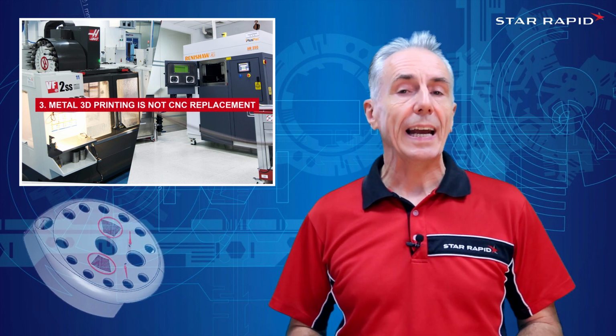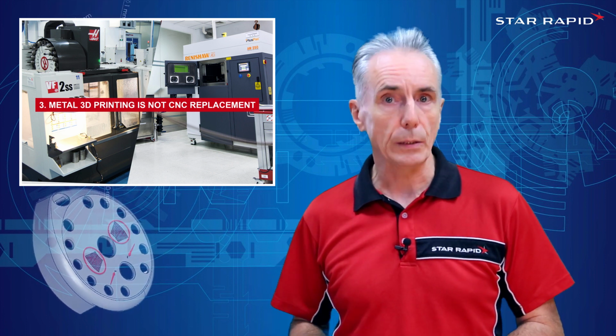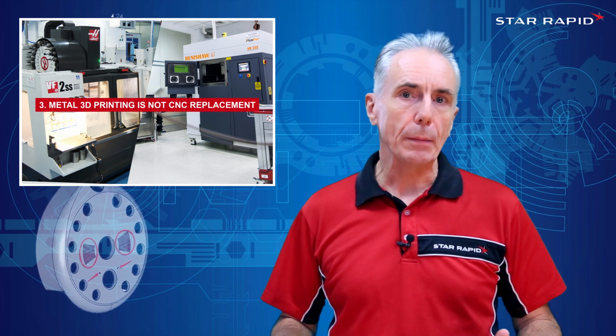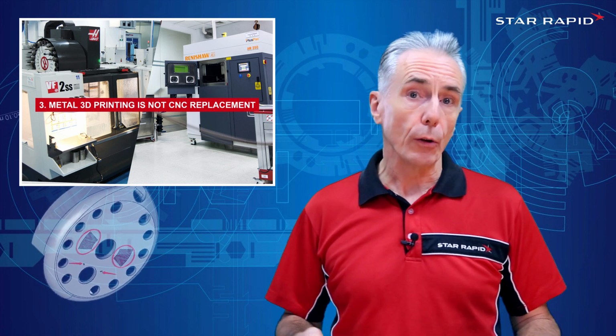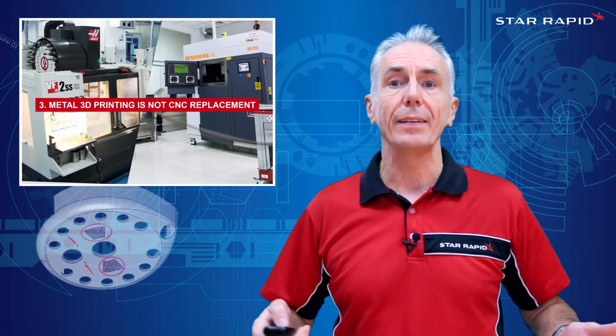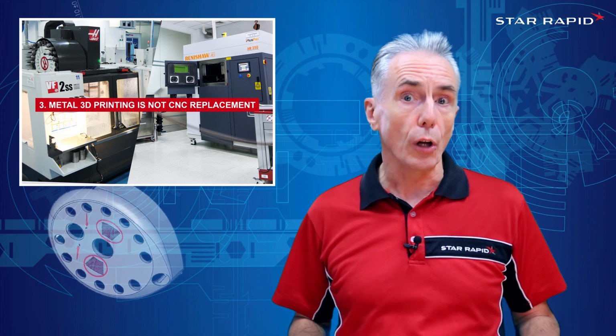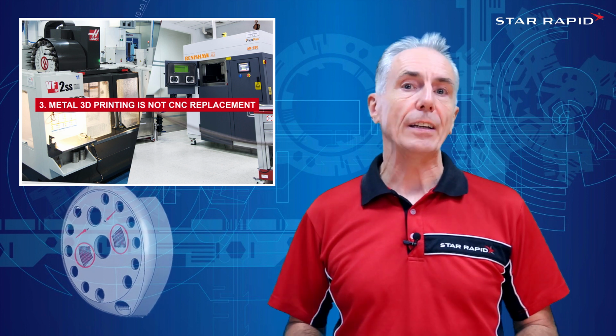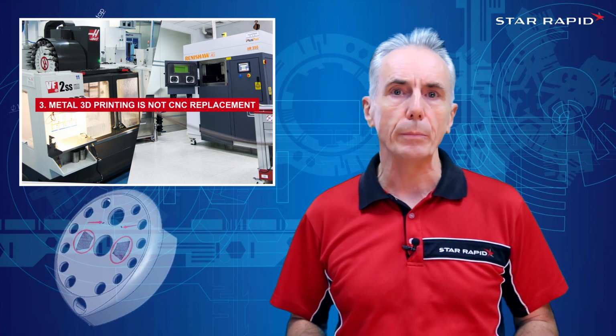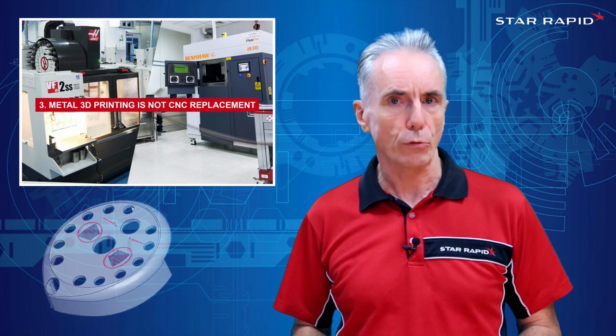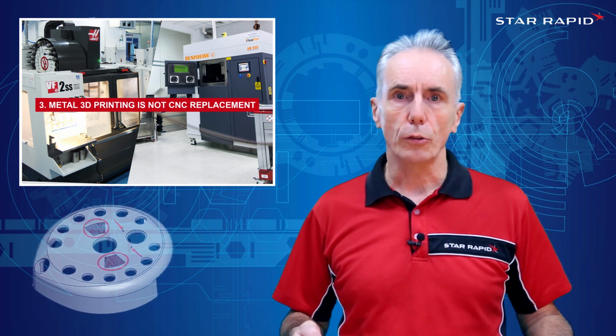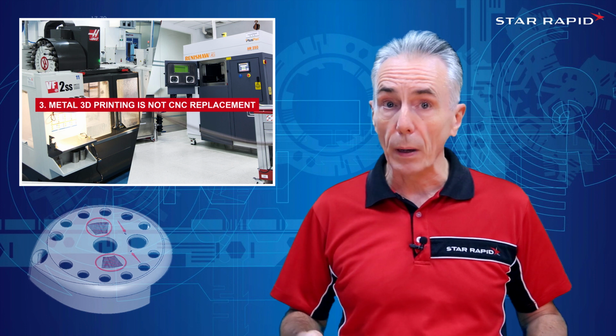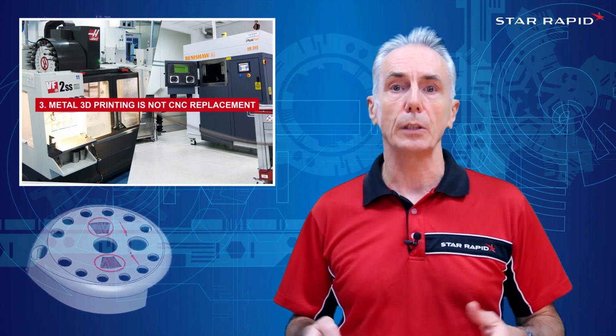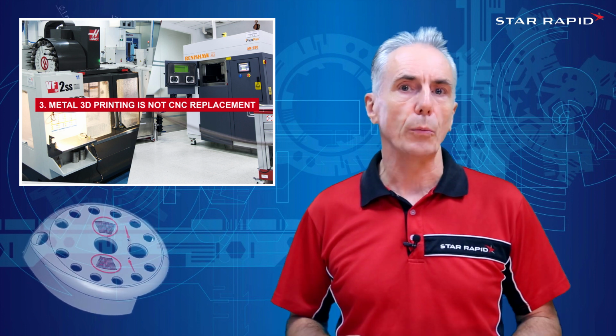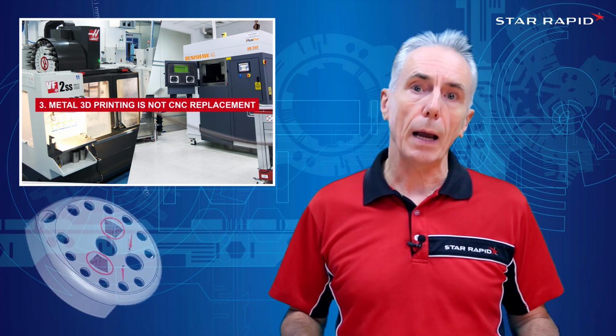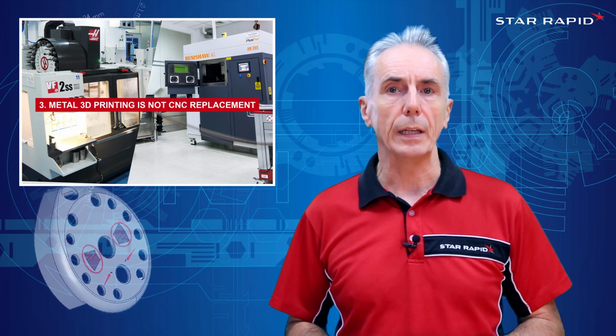Metal 3D printing is not a CNC replacement. Too many people expect high precision from metal 3D printing, and although the precision of these technologies is way better than it used to be 10 years ago, it is still not precision machining. Typically you can expect plus or minus 0.1 to 0.2 millimeters, but this is not a hard and fast rule. Parts can buckle and twist due to the design or the volume of the parts, so you can occasionally see parts as much as 1 or even 2 millimeters away from CAD. It's rare, but it does happen if the general rules of metal 3D printing are broken.